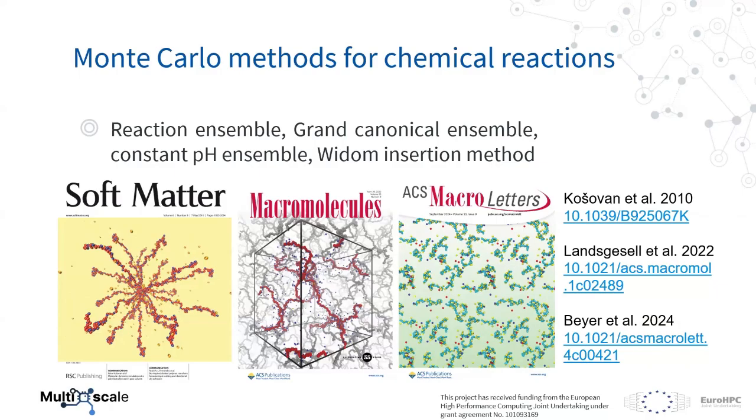In the middle picture, we have a 3D network of a polymer hydrogel, which has this characteristic that when you add moisture to the dry powder, it will absorb it. It will release protons in a solution because all the acidic groups want to be negatively charged, and the polymer will then be electrostatically repelled by itself, and it will swell. But if you add salt to the system, you will screen the Coulomb interaction, and the polymer will now collapse. And so you will observe the swelling behavior of the network.